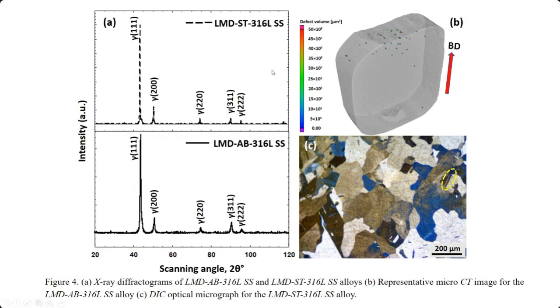We did XRD to make sure there is no further formation of any phases happening, but the microstructure is getting equiaxed now. Instead of a variation in the microstructure as columnar and equiaxed, coarse and fine equiaxed, we have a homogenized microstructure of equiaxed grains all throughout, with no variation in the phase formation.